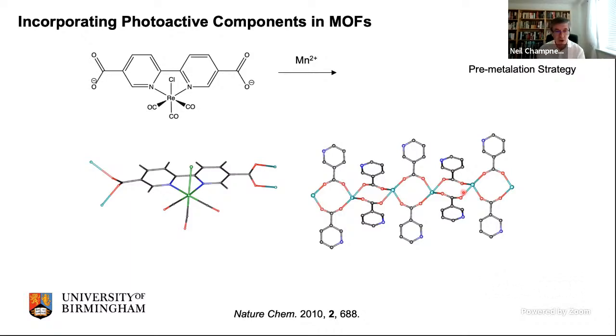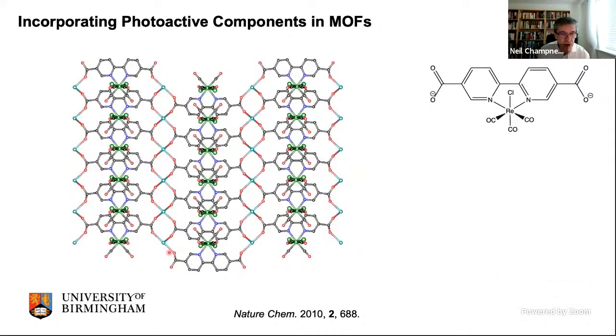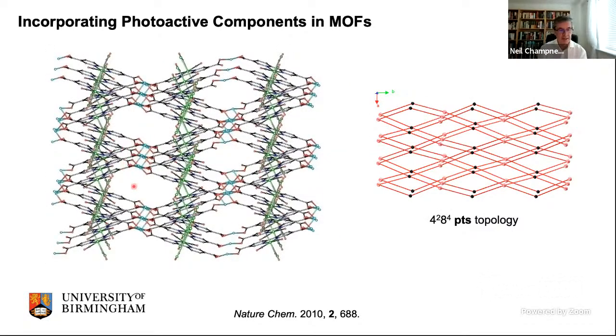So we have these manganese carboxylate chains. Here you can see the manganese carboxylate chains being bridged through the rhenium complexes. And if you look from this direction, here are our manganese carboxylate chains once again, and here are our rhenium complexes, which are now attached to the struts of a framework. So they're actually built into the framework, sitting on the framework structure. At this point, I'm just going to point out that this particular structure looks porous. It isn't. It's important to know that this isn't a porous structure. It's just because of the way the picture looks. It's not significant. So we now have our rhenium complex supported by the MOF.